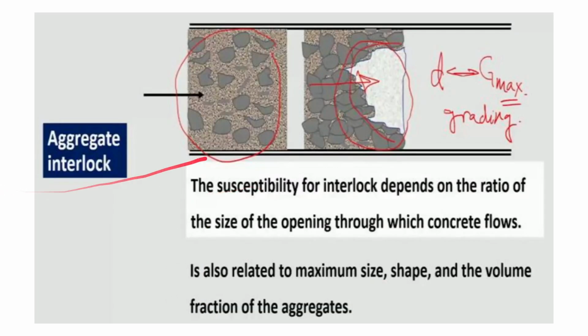Again, if we go into the case of aggregate interlocking, we will find that the susceptibility for interlock depends on the ratio of the size of the opening through which the concrete flows. So it is also related to maximum size, shape, and the volume fraction of the aggregates. The opening size and various other parameters will also play a major part for the interlocking susceptibility. So all these criteria have to be kept in mind.